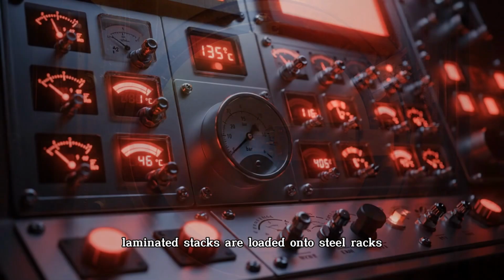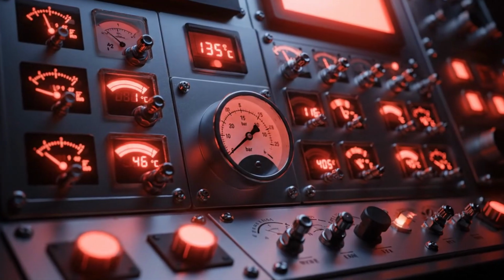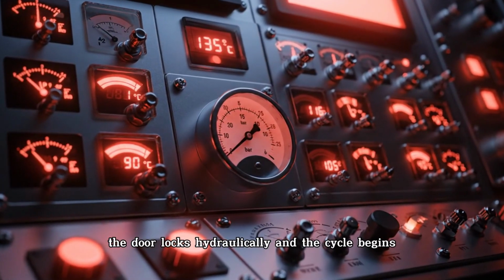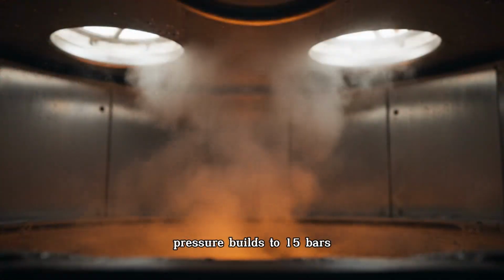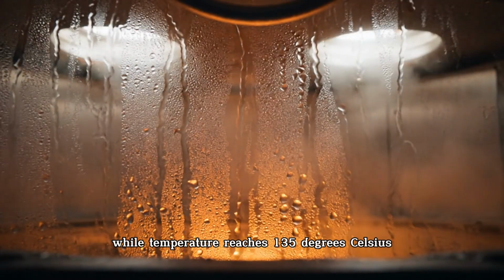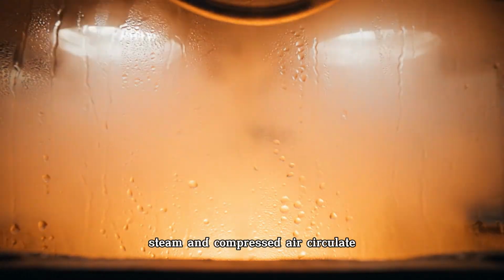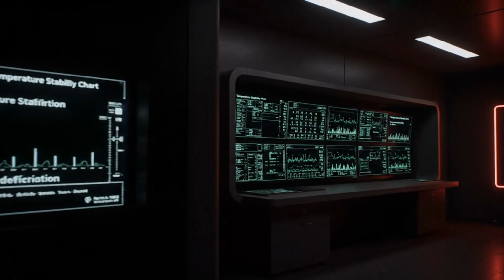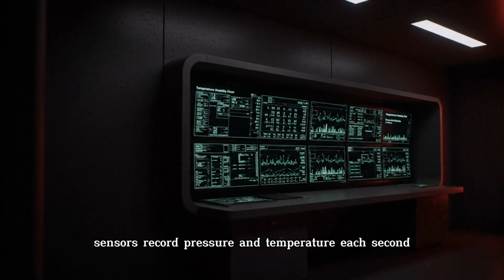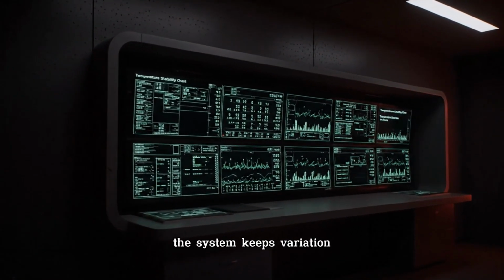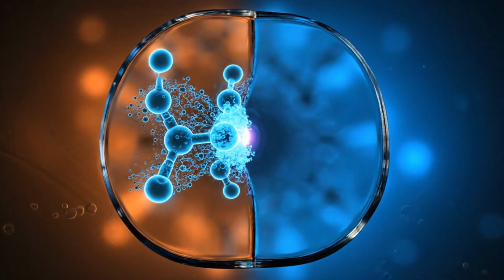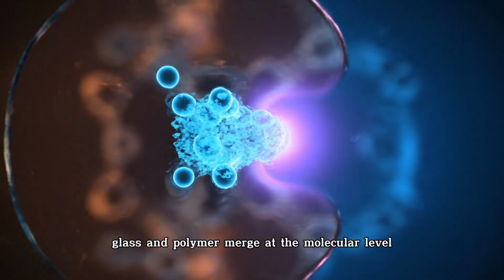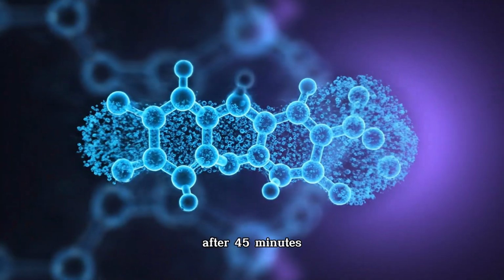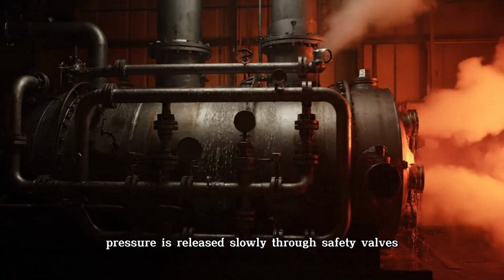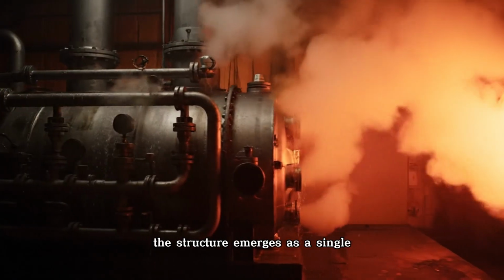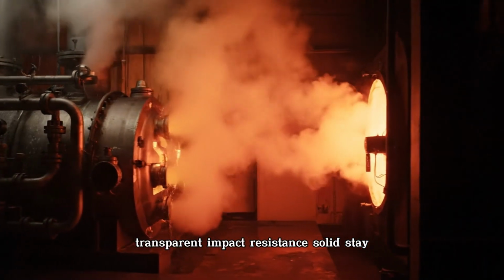Laminated stacks are loaded onto steel racks and moved into the autoclave. The door locks hydraulically and the cycle begins. Pressure builds to 15 bars, while temperature reaches 135 degrees Celsius. Steam and compressed air circulate to ensure uniform heat. Sensors record pressure and temperature each second. The system keeps variation within plus or minus 3 degrees Celsius. At this point, glass and polymer merge at the molecular level. After 45 minutes, pressure is released slowly through safety valves. The structure emerges as a single, transparent, impact-resistant solid.